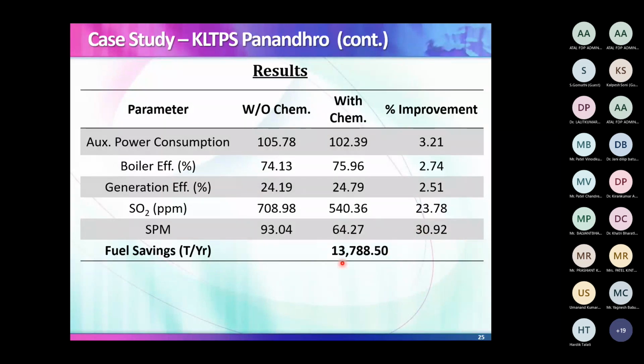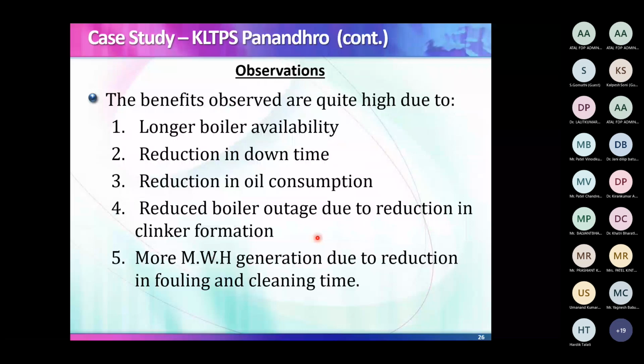What observations did we make later on? This has been continuously working since May 97, 98 till now. They are still using this additive. And what benefit has been observed? There is a longer boiler availability and a reduction in downtime, and a reduction in oil consumption, because once the boiler is down, you have to fire oil. So oil consumption will increase. It has come down because downtime has come down. Reduced boiler outages due to reduction in clinker formation, and more M.W.H generation due to reduction in fouling and cleaning time. This is the beauty of this particular additive. These are the advantages which we are getting for more than 20 years.